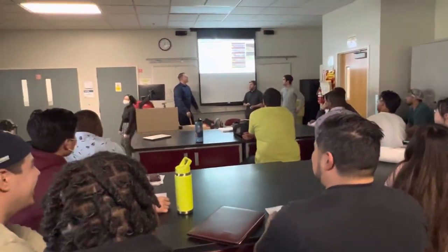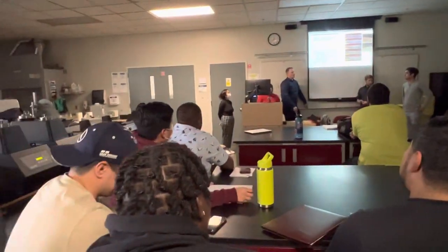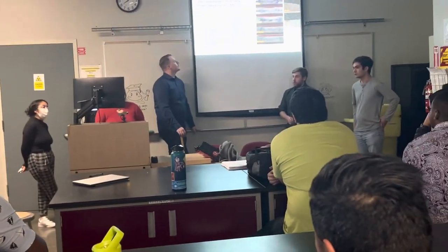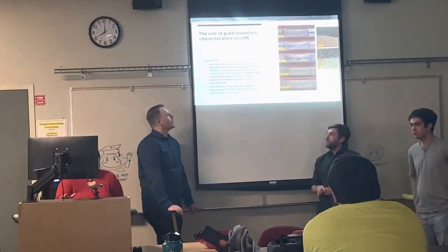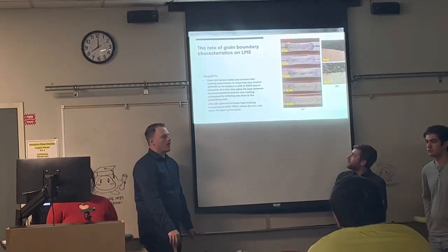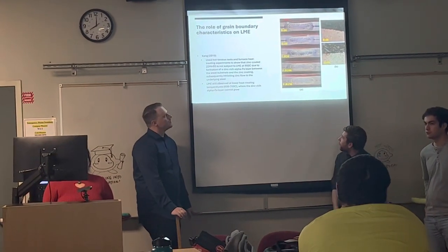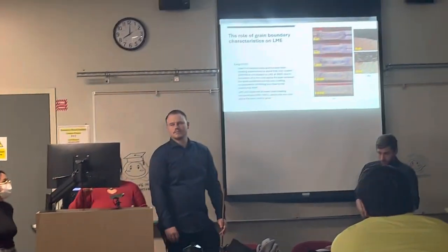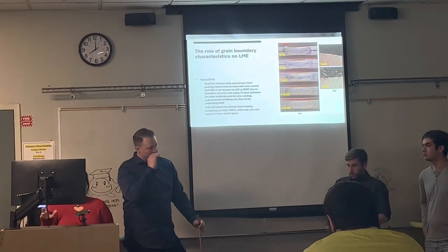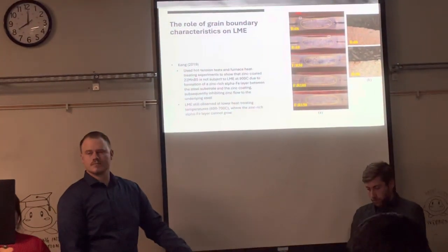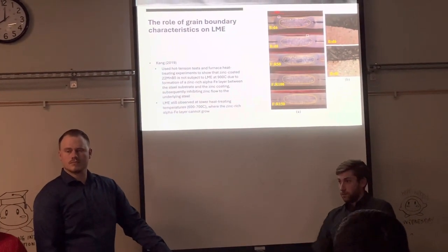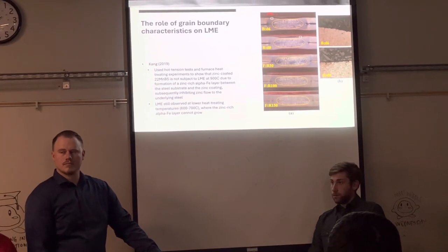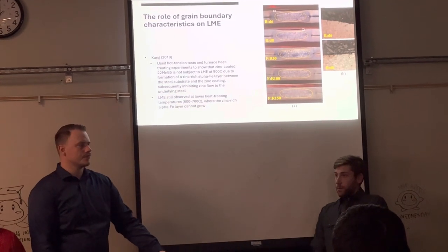And lastly, we have the role of grain boundary characteristics on liquid metal embrittlement. So Kang, just like he did in 2019, did another experiment using hot tension tests and furnace heat treating experiments to show that zinc-coated 22 manganese boron steel is not subject to liquid metal embrittlement at 900 degrees centigrade, as previously mentioned.